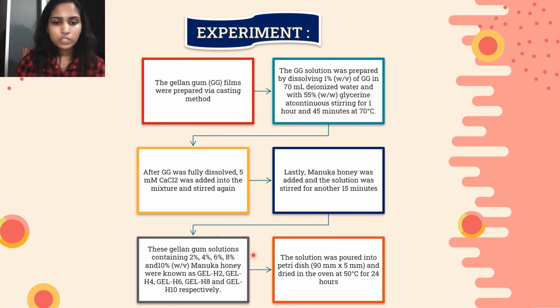These Gellan gum solutions containing 2%, 4%, 6%, 8%, and 10% Manuka honey were known as Gel H2, Gel H4, H6, H8, and H10 respectively. The solution was poured into petri dish and dried in the oven at 50 degrees Celsius for 24 hours.